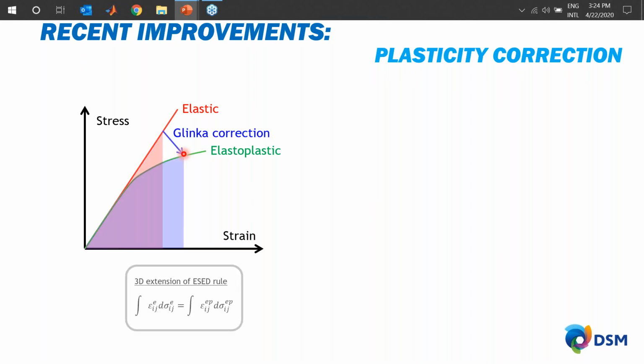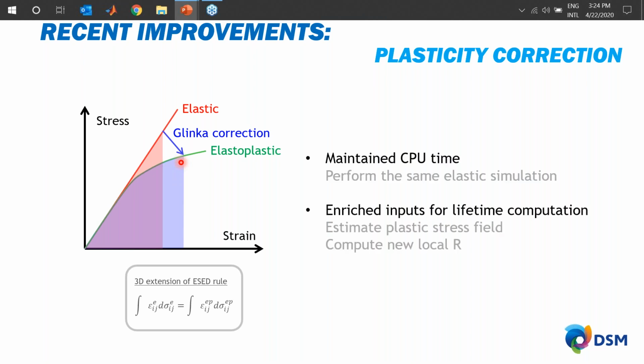This can be solved because you can correct for that by, for example, using the Glinka correction, very similar to the Neuber correction, as you might be aware of, where you use the elastic free energy density and look for the equivalent one in the elastic-plastic range to knock down your local stress levels. And this brings us to the advantage of using DIGIMAT, because the colleagues from DIGIMAT are very good at predicting the elastoplastic material performance for a lot of different fiber orientations.